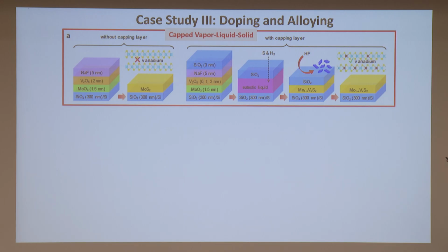After a few rounds, maybe you lose the vacancies in the best optimized cluster shape, and maybe the edge also reconstructs into a more inert state. So a possible solution to replace the edge contribution or the defect engineered surface is that we do doping or alloying. So eventually, you want to create a surface that is fully connected, but then some of the atoms are heteroatoms. So this is the idea that initially I thought was simple.